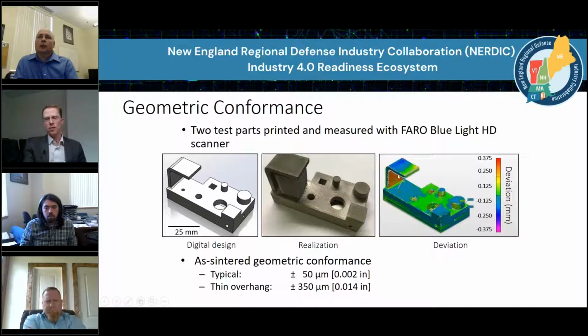Now for this thin overhang, it's kind of a tough part, and there's an interface on the bottom and an interface on the top, so it's going to want to sag more. There it was plus or minus 350 microns, or about 0.014 inch. And so it's fairly close, but it is a near net shape process.